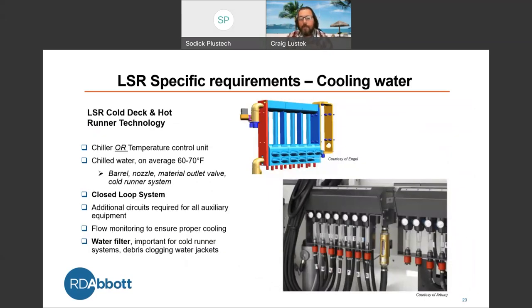Cooling water requirements: a chiller or a temperature control unit. Chilled water on average, we want to look at between, again, 60 to 70 degrees Fahrenheit. And we want this for our barrel, our nozzle, a material outlet valve, and our cold runner system. We want this on a closed loop system. So if we have one chiller tied to one machine, or we have one chiller tied to numerous machines, we just want to make sure that we have enough tonnage on that chiller to cool properly for each machine. Additional circuits, it's always nice to get those additional circuits for different auxiliary equipment, for your static mixer, for your material outlet valve.